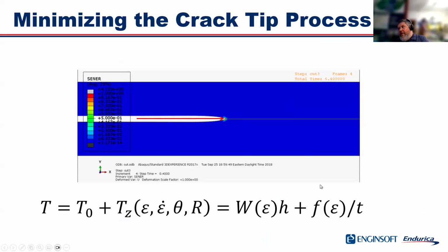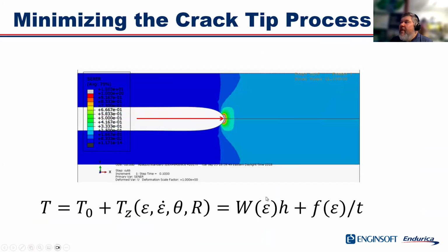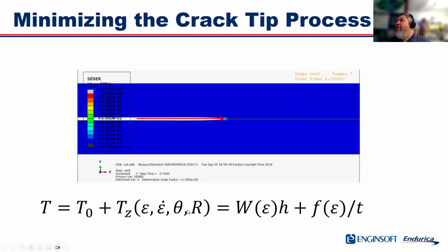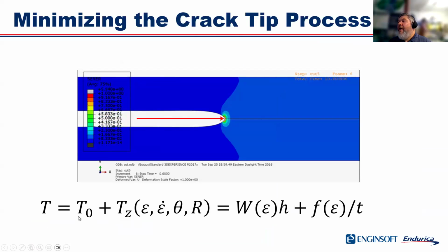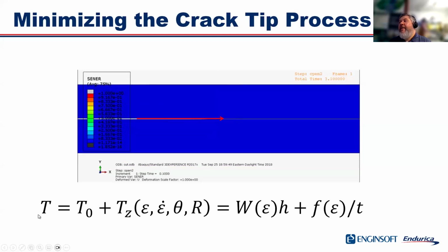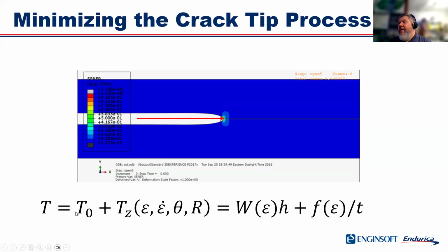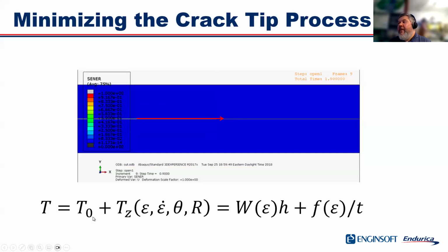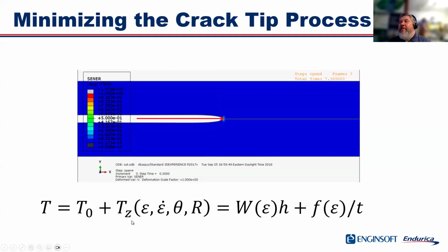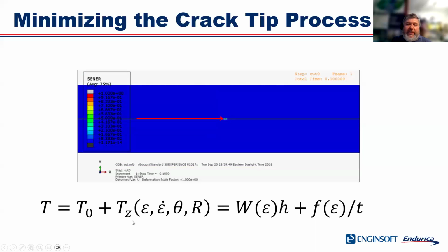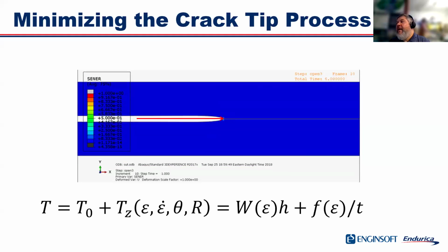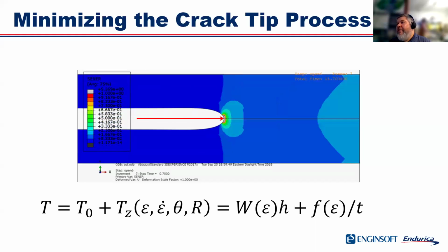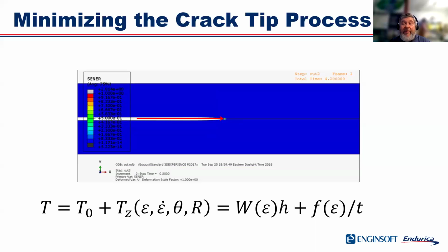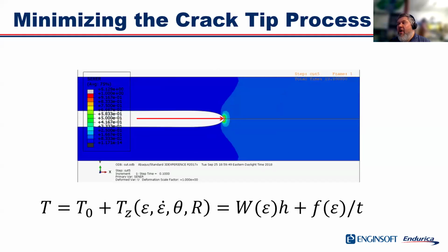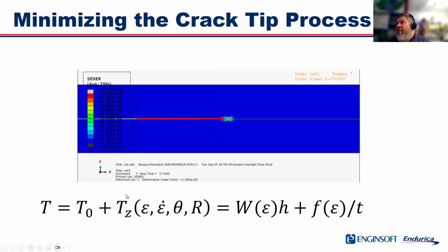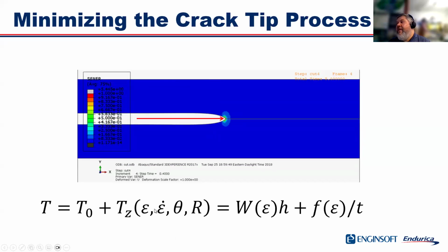To talk a little bit more about how the measurement works, I showed before how the tearing energy, when the crack is growing at a certain rate, is the sum of two parts. You've got the intrinsic strength that I want to know, T naught, and then you've got this TZ part that represents all of the dissipative processes. And if the crack is growing quickly, that's going to be a very large number that'll completely bury T naught. So in the experiment, what we want to do is find a way to get rid of TZ.